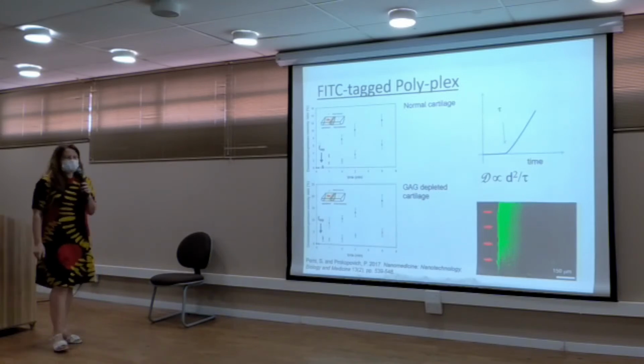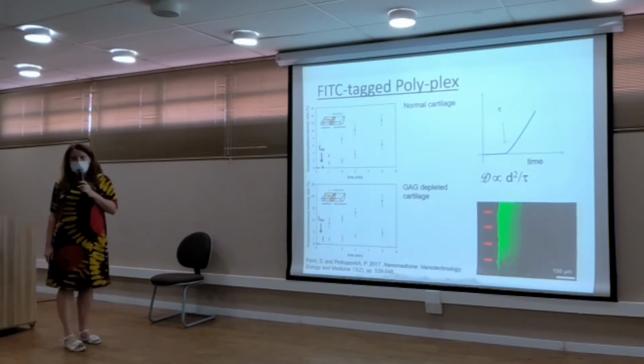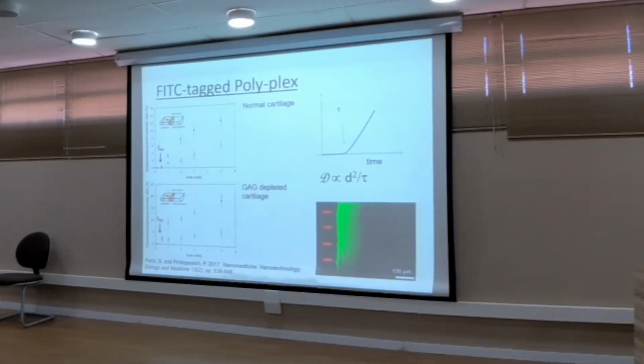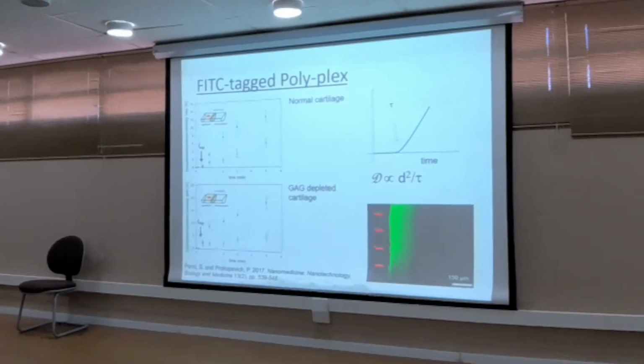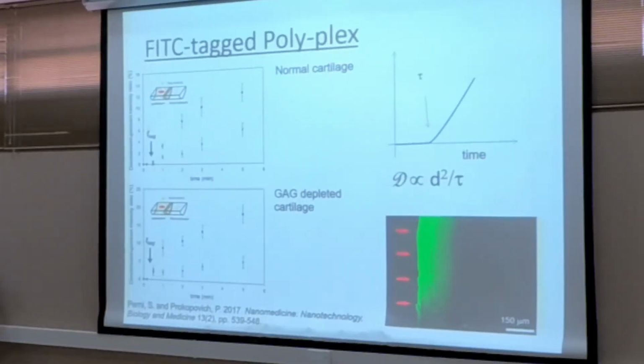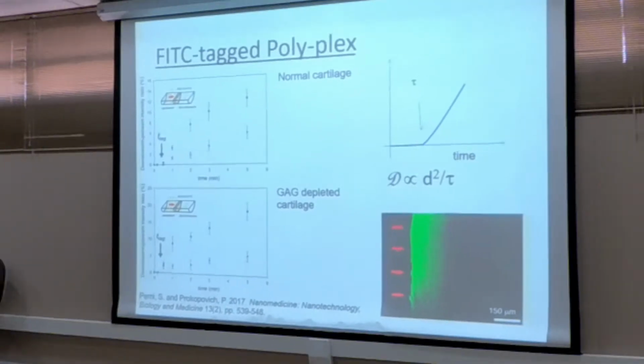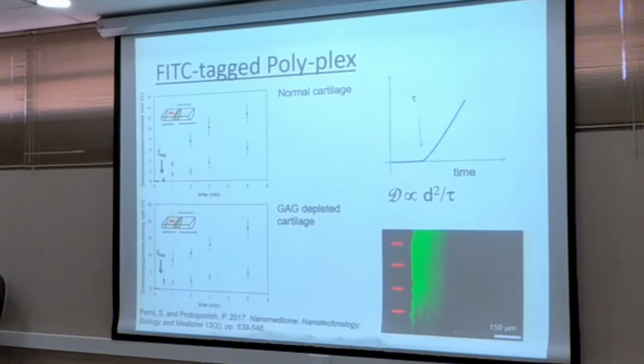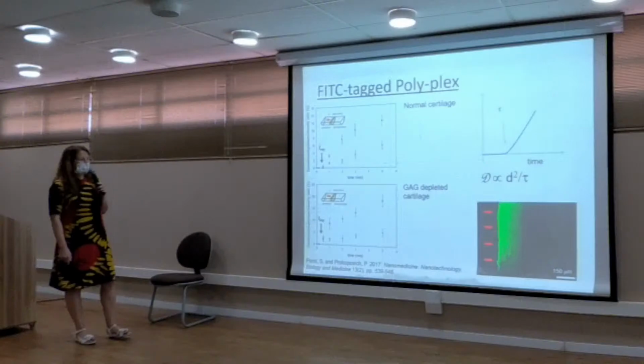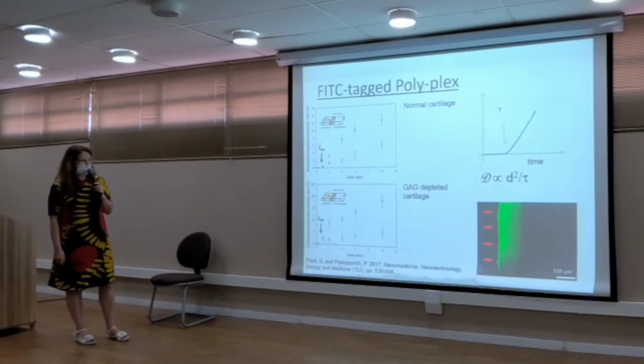We also wanted to make sure that our polyplex system can go through the cartilage tissue. So we wanted to ensure that it doesn't really stay on the surface of the cartilage, the superficial zone. It goes through the whole depth of the cartilage material. So we measured the diffusion coefficient, and by fluorescent labeling of our polyplex delivery system, we showed that our nanosystem is able to go through the whole thickness of the cartilage material.